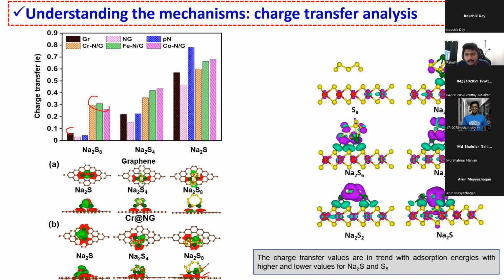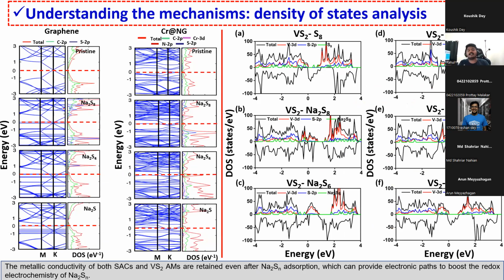Even for VS2, you can see that the charge is accumulated at the interface and the charge is depleted from the polysulfide. That basically indicates that the charge is getting transferred from the polysulfide to the substrate. That's the reason why we are getting a positive charge transfer value in our calculations. If we get a positive charge transfer, that indicates that the charge is getting transferred from the polysulfide to the substrate.